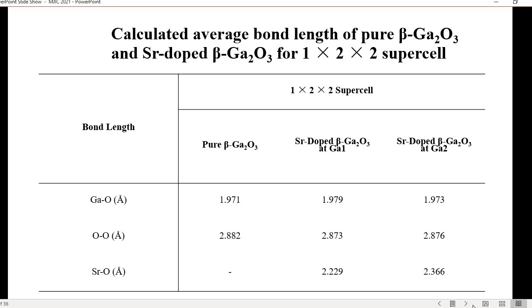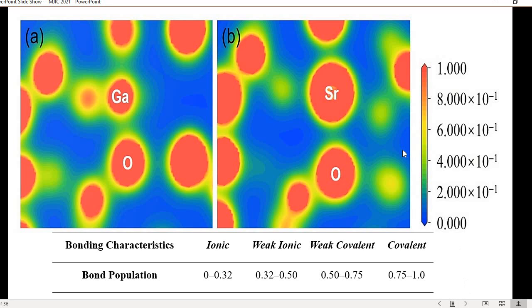Now for the spatial electron density map. Part A shows pure gallium oxide, where atoms mostly reside in the red color region, indicating a strong covalent nature. After implanting the strontium atom, the bonding characteristic changes — strontium-doped gallium oxide is located in the weak ionic bonding region, shown mostly in the green color region from Materials Studio.